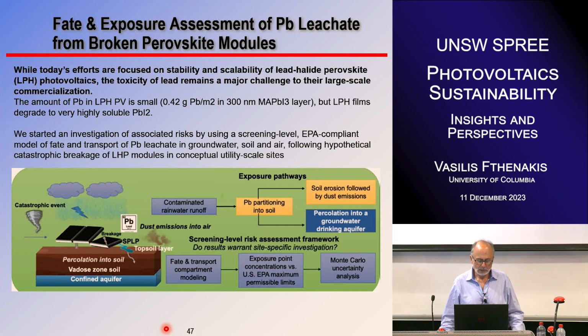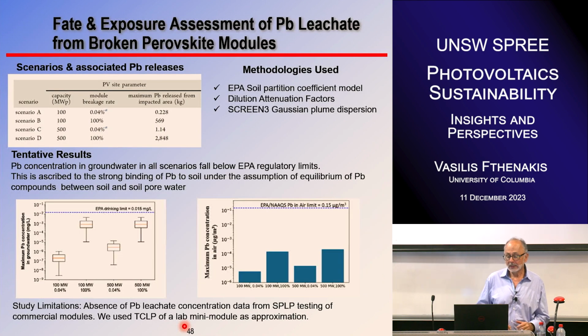So we did a study just published, actually I have one PhD student that I co-advised with Drexel University, and we did some screening analysis there, assuming that you have breakage of modules from 100 megawatt and 500 megawatt solar farms that use perovskites, and that rain will take the lead down to the topsoil, and then from there it could go to water, groundwater, and so on. It's interesting that we assume that it goes first into the soil. So what we found, based on the screening analysis using again the EPA's soil partition coefficient model, the dilution attenuation factors going from soil to water, and a Gaussian plume dispersion, assuming that some dust can be airborne, but only from one centimeter of the depth, and it could be dispersed in there.